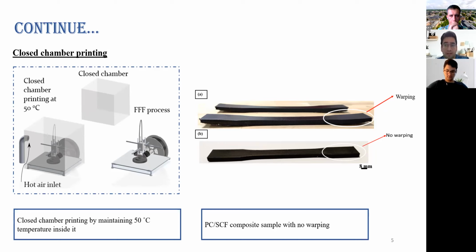But the problem with high temperature materials is that if we use them in 3D printers, they warp. As you can see in figure A, they warped. If they warp, the quality and the mechanical performance of that part is going to be bad, so you can't use that material. So you have to resolve that warping issue. In our lab, we figured out a technique to reduce that warping, which is closed chamber printing.